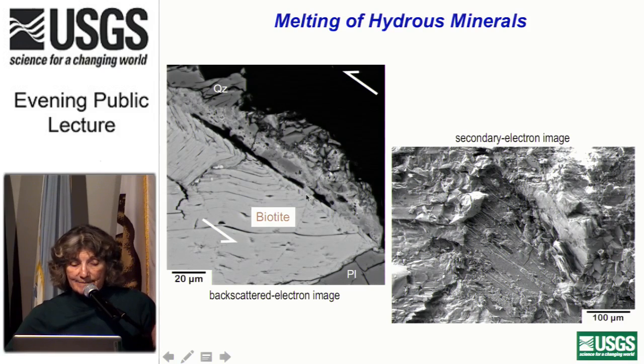And it separated and apparently drove out whatever melt was here and pushed it out along the fault surface, which is why we've got all these biotite-rich bands, zones, within the melt in the glass now that are nowhere near a biotite crystal. So all of these things quenched, and we have these voids left over. This must have been a rather exciting time here, because all of the remaining material up here is broken up and fragmented, and there are a lot of small gas bubbles up here as well.